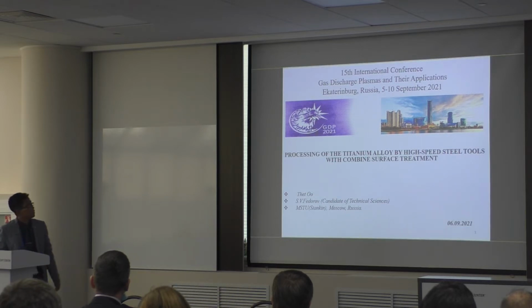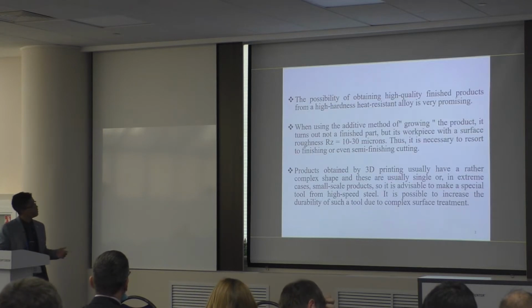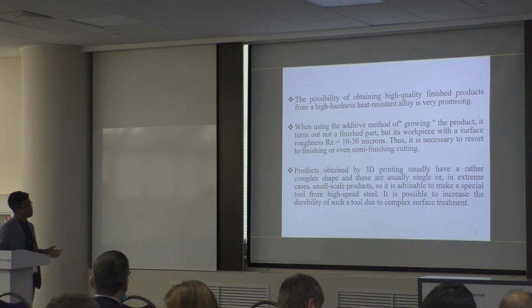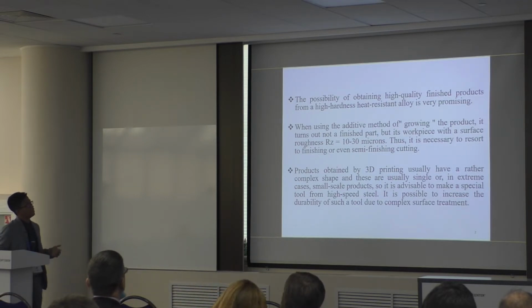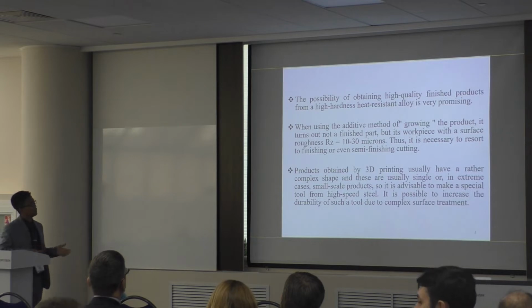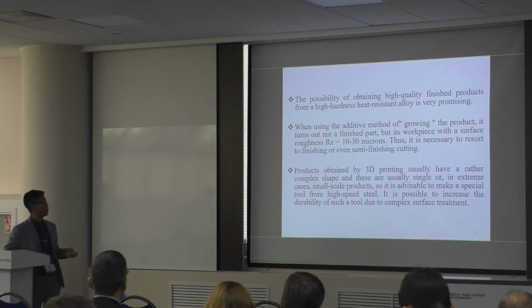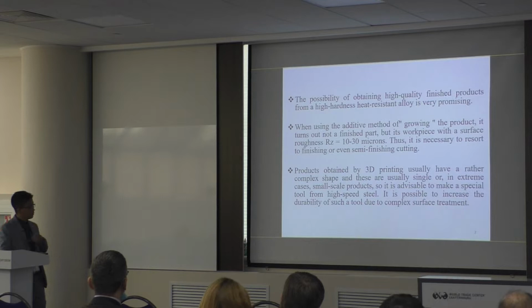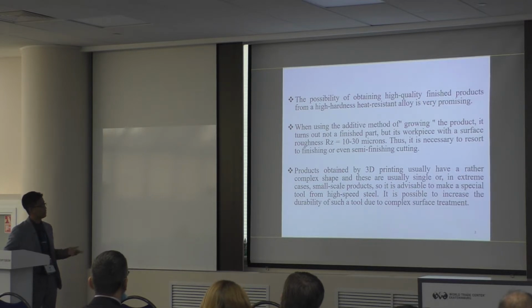As you can see on the screen, our topic today is processing of the titanium alloy by high-speed steel tool with combined surface treatment. The possibility of obtaining a high-quality finished product from a heat-resistant alloy is very promising. When using the additive method of growing the product, it turns out not a finished part, but one with a surface roughness Rz = 10 to 30 microns. Thus, it is necessary to resort to finishing or even semi-finishing cutting.